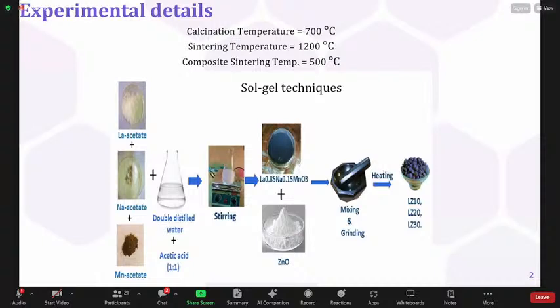Okay, so this is the route of the sol-gel method, in which acetate precursors were used: La acetate, sodium acetate, and Mn acetate are mixed in distilled water and acetic acid. Then after stirring using the hot plate, we prepared the LNMO, and in different stoichiometry we add the LNMO at 10%, 20%, and 30% in ZnO micro state, and the calcination provided was 700 degrees centigrade. Sintering temperature was 1200 degrees centigrade, and composite sintering temperature was 500 degrees centigrade.